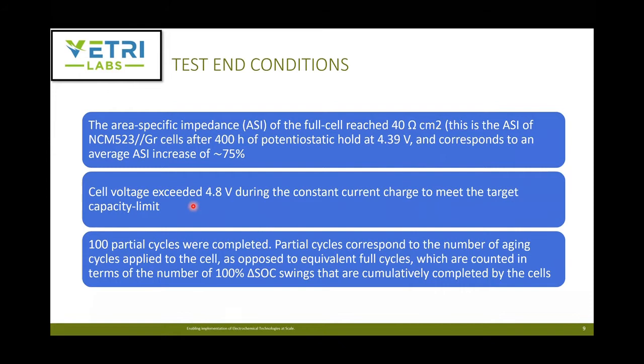Or if the cell voltage exceeded 4.8 volts during the constant current charge, that was called the test end condition. And the third condition was 100 partial cycles were completed. These partial cycles essentially meant that you ended at this SOC that you wanted, right? And they also did some calculations later using the total charge as an equivalent 100% SOC, and we'll look at that later in the results.